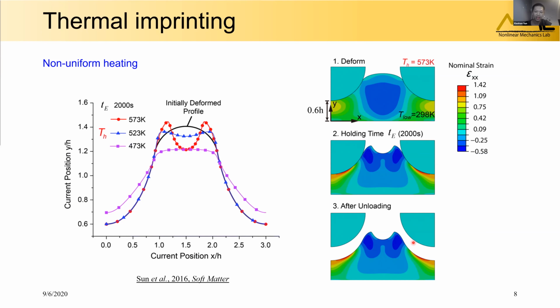When the heat conduction is relatively slow, that is, when the high temperature and the short time are used, the high temperature will be confined to the region near the contact interface. Then the localized stress relaxation can cause the material in this region to be compressed more. And then it will creep up due to the Poisson's effect, finally forming the final imprint significantly deviating from the initially deformed profile.